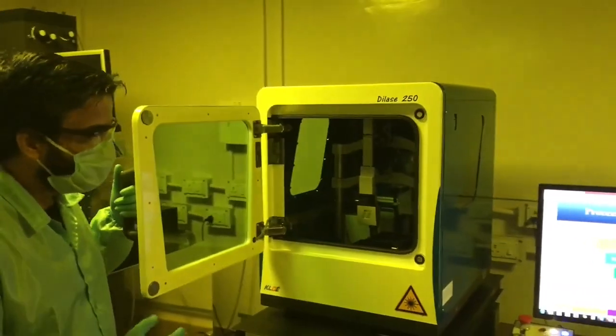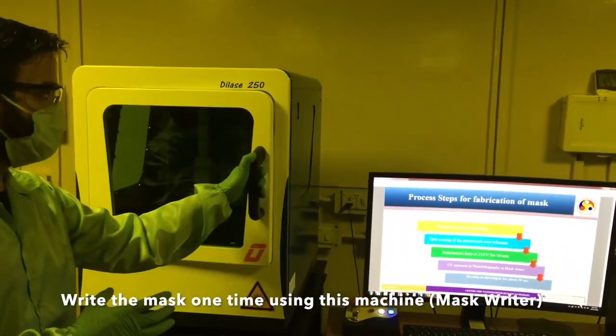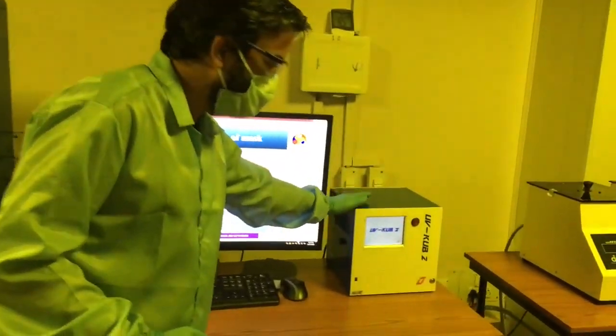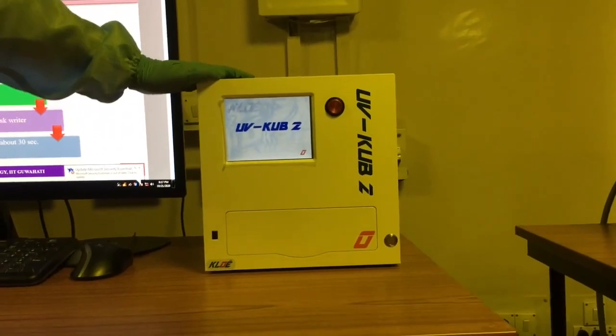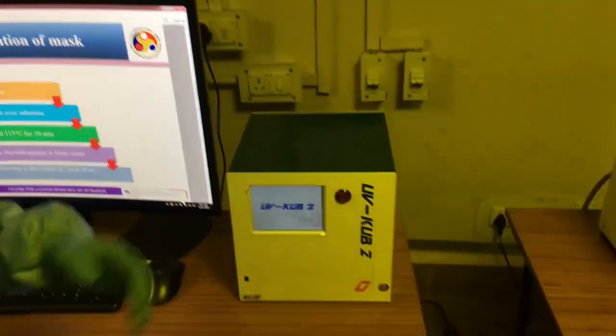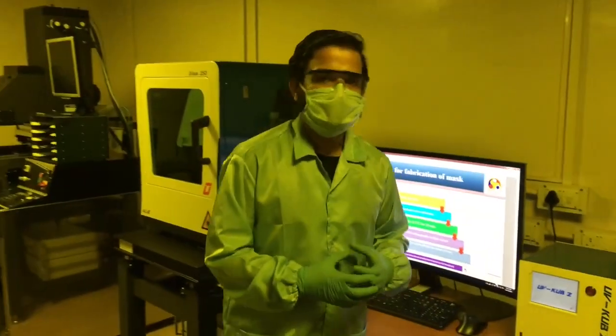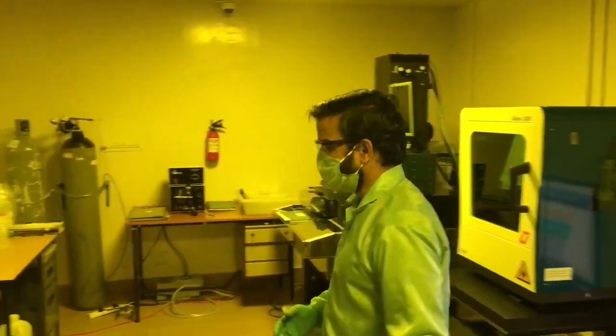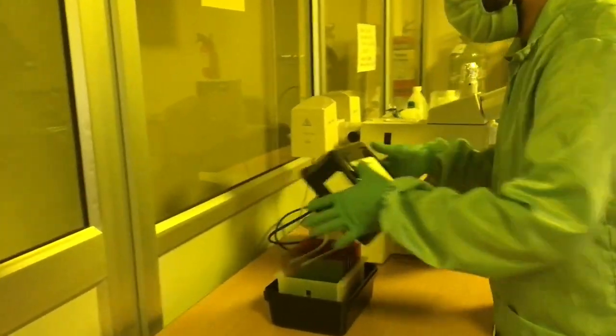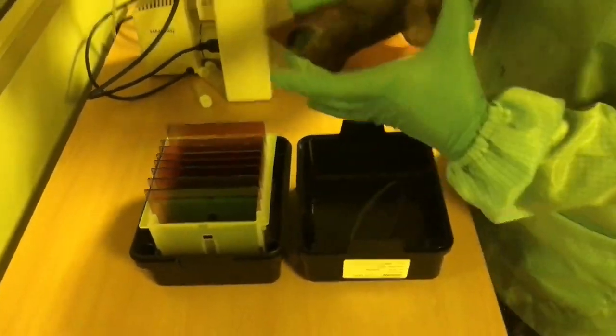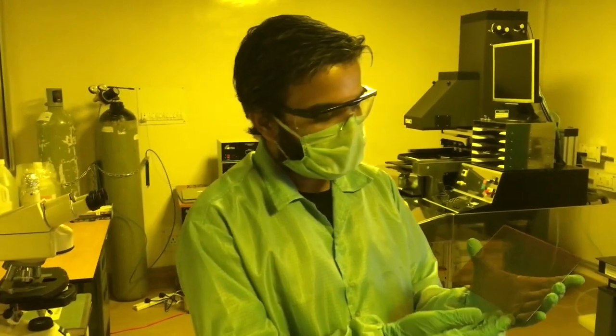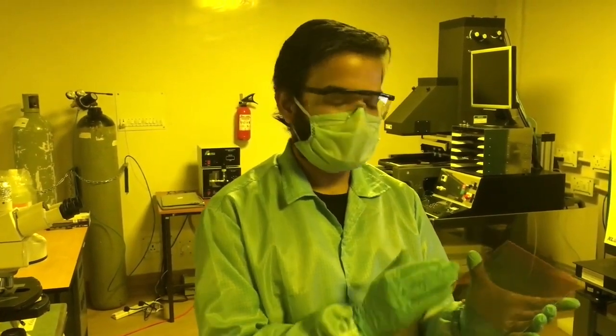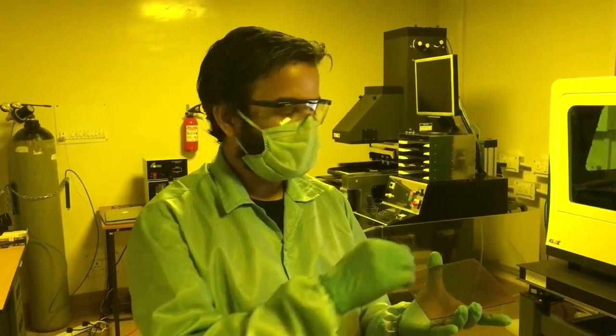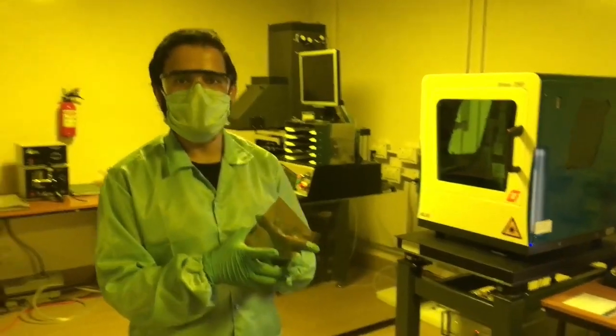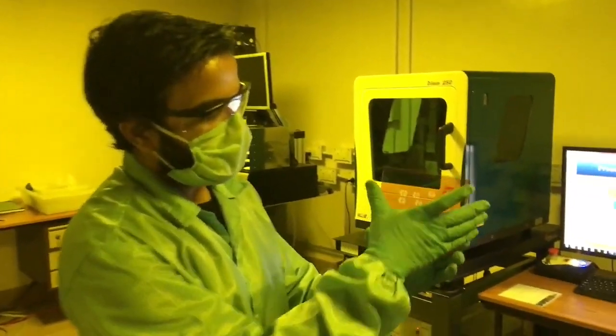So in order to save time, we can write the mask one time and then use this UV box for the exposure. Our photoresist is sensitive to this UV radiation. So the UV radiation will fall and the patterns will appear over the silicon wafer. So this is the wafer, and this is the mask which I was talking about. This is a soda lime glass over which a chromium coating is there, followed by the photoresist coating. So we can write the designs directly with this machine, develop it, etch the chromium, and you can see the final designs will appear like this.